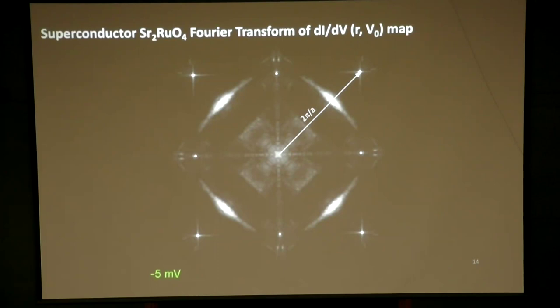I want to pause here for a moment, because I want to show you what information this Fourier transform actually contains. These four dots here are the Bragg peaks, so they represent the lattice. The distance from the center to the Bragg peak is 2π over the lattice constant. So if you can measure the distance from here to here, you can invert that to get the lattice constant. Any changes in the position of these peaks you can get from the Fourier transform, and that tells you if there are any changes in the lattice constant in your sample.